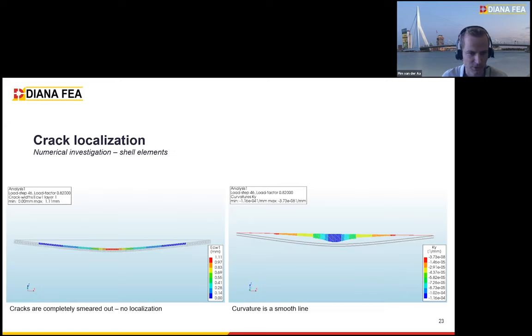Then on the left side, you see your crack width, which is strongly related, of course, to the strain, only multiplied with the bandwidth. So also the strain would be smeared out, as it's shown here. And on the right side, you see actually the curvature. So the curvature is also a bit of a smooth line, but not completely identical to the shape of the bending moment. That's because in the middle, where the largest cracks are occurring, you see, of course, a reduction of the stiffness. And if you see a reduction of the stiffness, but the bending moment remains the same, then you will see an increase in the curvature.